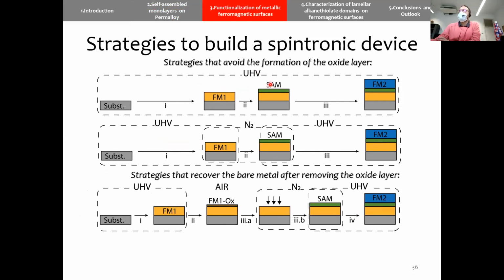So if you possess a UHV facility or a clean room facility, you can follow path 1 or path 2. So without exposing, in this case by sublimation, or in this case using a glove box, you can form an oxide-free substrate. But what we want to develop is more or less strategy 3, where we can fabricate the surface in some place of the world. The surface is sent in air, so it can get oxidized. And what we want to observe is how we can get rid of this oxide without affecting the metallic bulk, grow the SAM, and then finish the complete device.